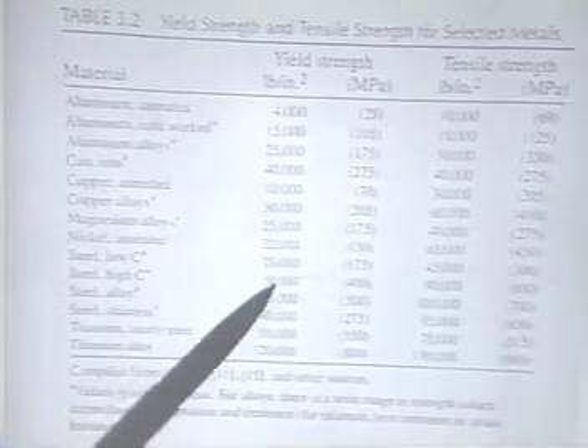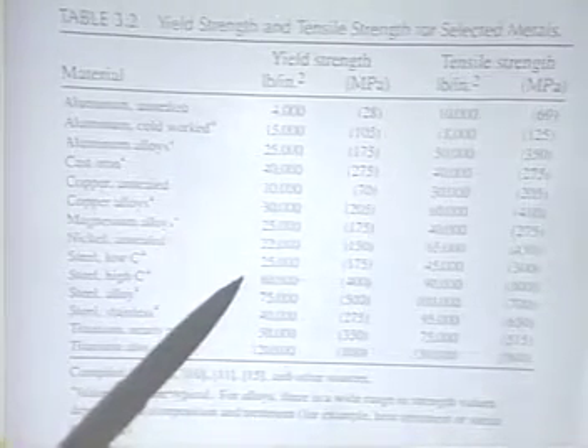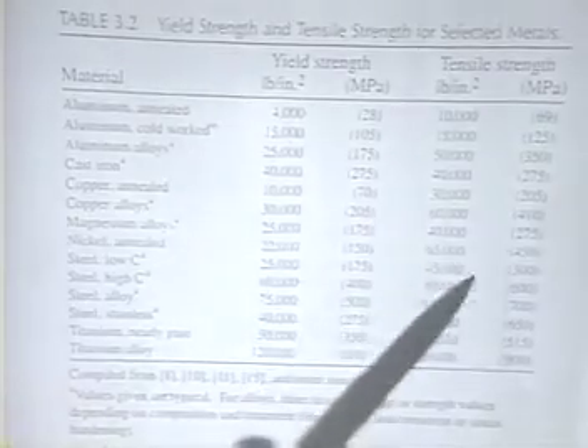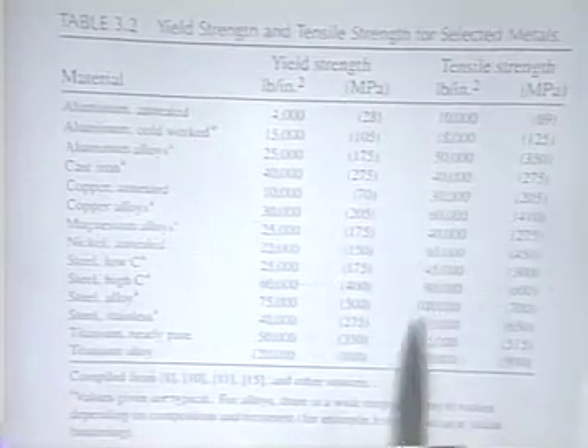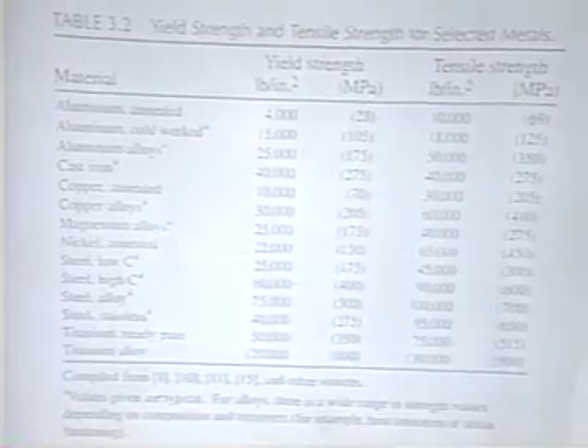Again, we can look at a low-carbon steel, which is like a 1020 steel, and we can see again the big difference between the aluminum and the low-carbon steel in terms of yield strength, when plastic deformation begins, and how much stress it can stand for uniform deformation. This is the tensile strength.